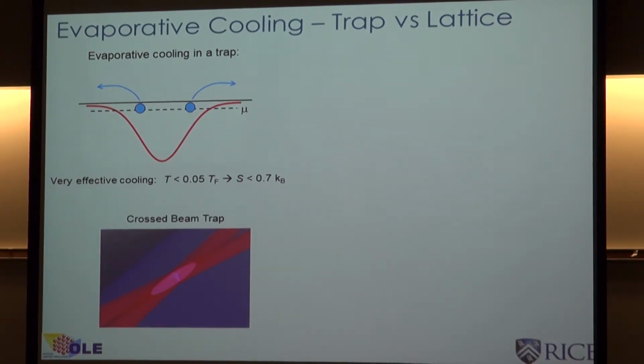Okay, good. Now I want to talk about the development of this new cooling technique in the optical lattice. In a trap, evaporative cooling is very powerful and a very efficient way of cooling initially, but also maintaining a low temperature. One thing that happens in traps is that there's a continual heating due to spontaneous emission, technical noise, fluctuations of the laser intensity, pointing instabilities, and so on. One way to mitigate that is to fill up this harmonic trapping volume all the way to the top, put the chemical potential very close to this continuum edge, and allow hot atoms in the distribution to escape.